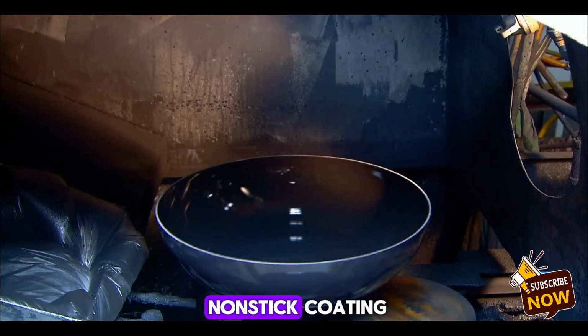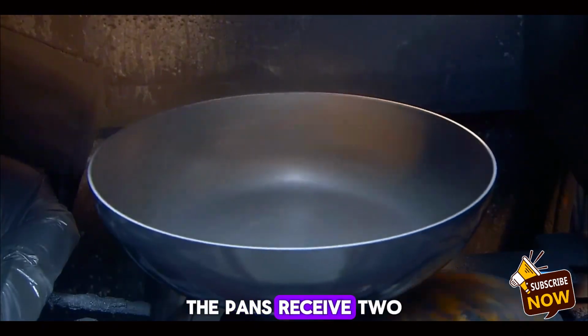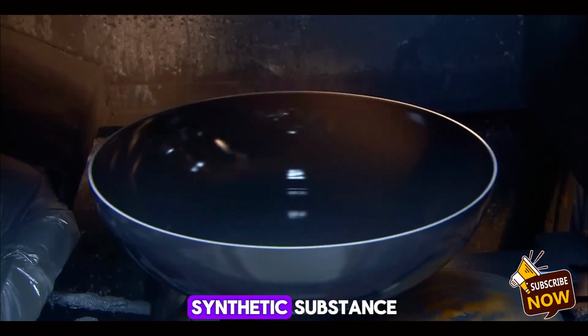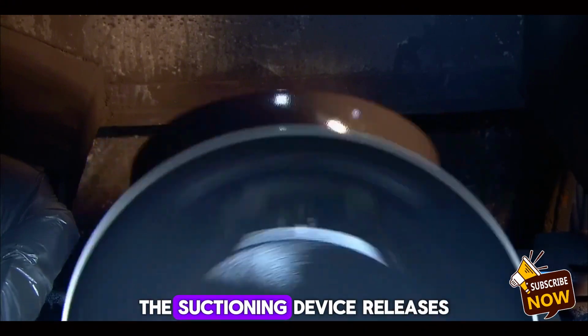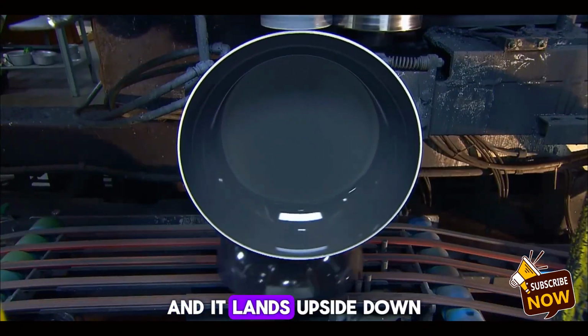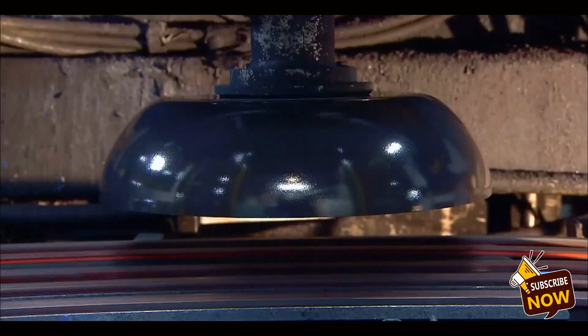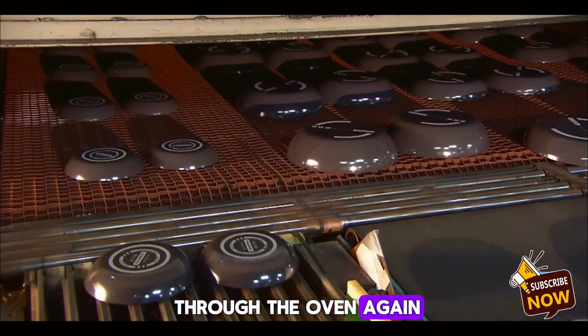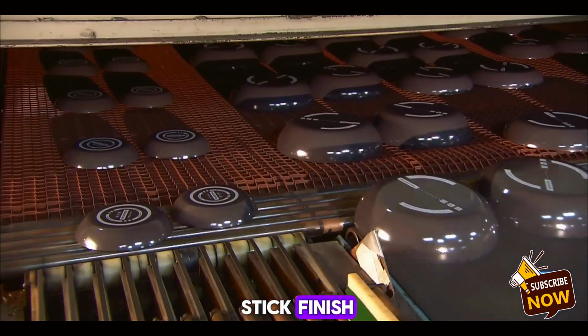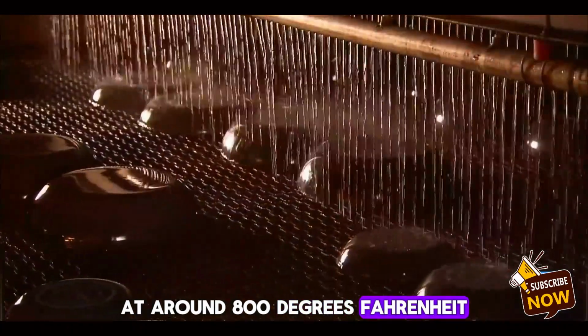It then applies the non-stick coating. The pans receive 2 layers of this non-stick synthetic substance. The suctioning device releases the pan and it lands upside down. Then the pans journey through the oven again to cure the non-stick finish at around 800 degrees Fahrenheit.